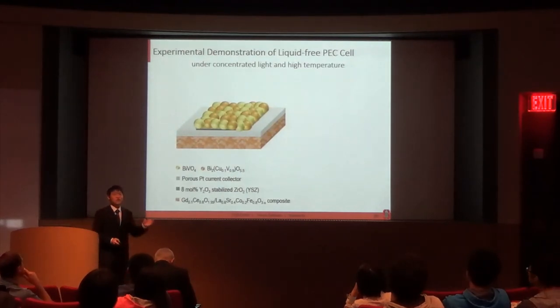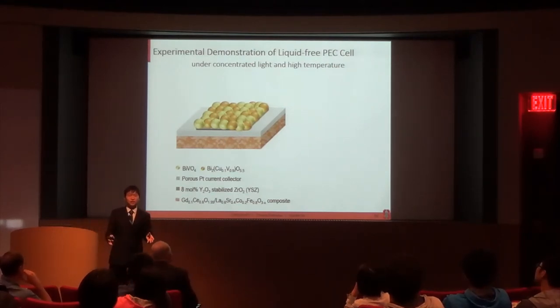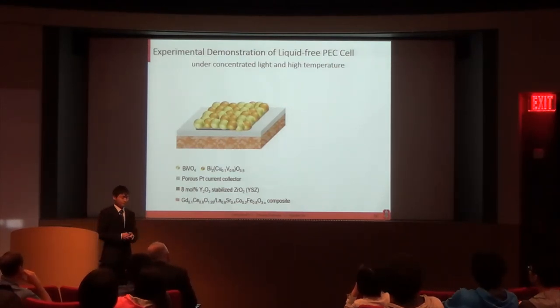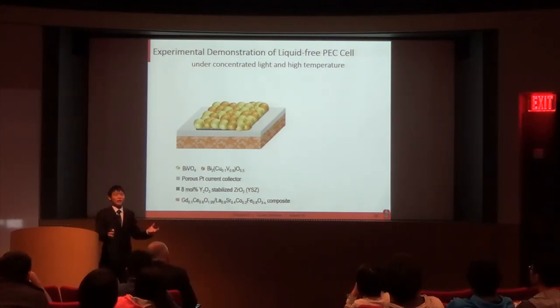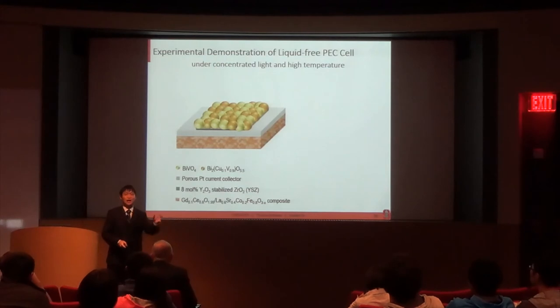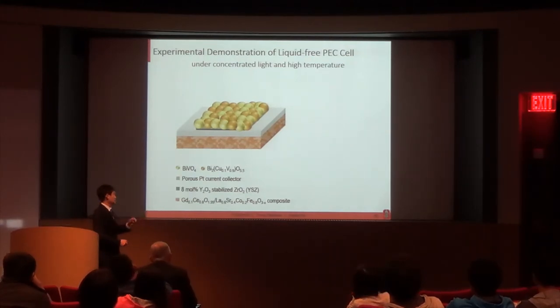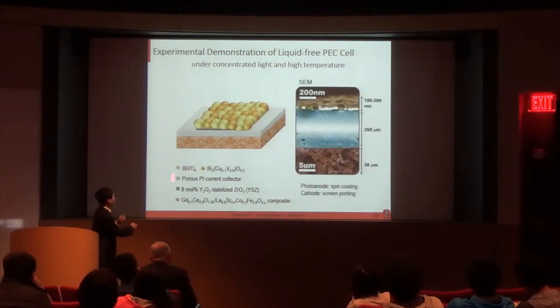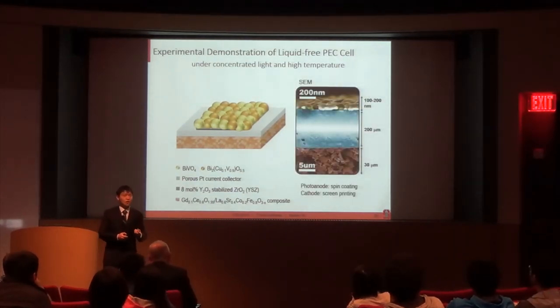And this is the first demonstration experimentally for the liquid-free PEC cell under high concentration sunlight and high temperature. So there's still ongoing efforts for device optimization that my colleagues and I will keep working on. But I'm very excited to show you this very first proof of concept result. So in this proof of concept, I still use the bismuth vanadate as the light absorbing material. Although we know that the optimal temperature for bismuth vanadate is slightly above ambient temperature, we still use this material because we have abundant knowledge of how this material behaves with increasing temperature.